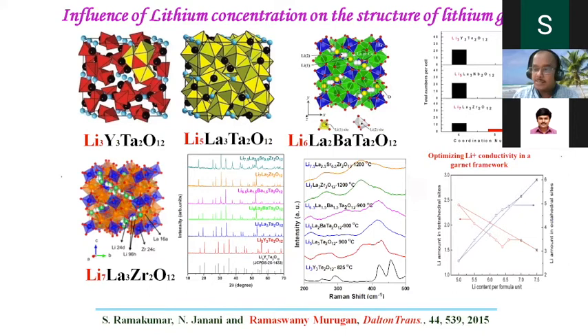Then we wanted to understand, because we moved from Li5 to Li6, Li6 to Li7, whether by increasing the lithium concentration by increasing the lattice constant, it is possible to improve the conductivity much more. Unfortunately, we were unable to increase it. And we wanted to understand what's happening between lithium 3 to Li7. When we have just lithium 3, lithium is housed exclusively in tetrahedral coordination. There is no vacancy. When I increase the lithium concentration to Li5 by expanding the lattice, what's happening?